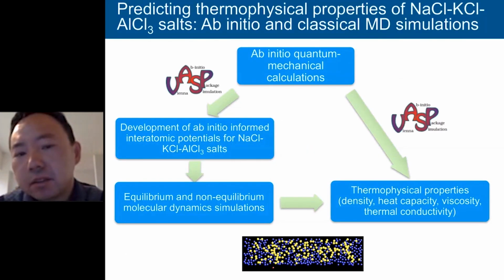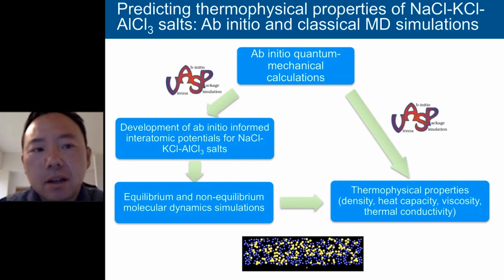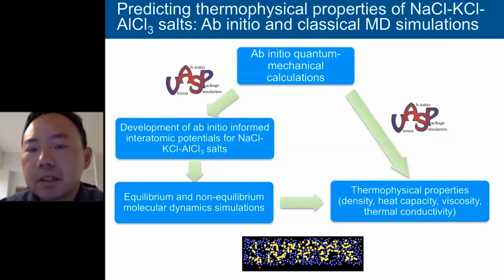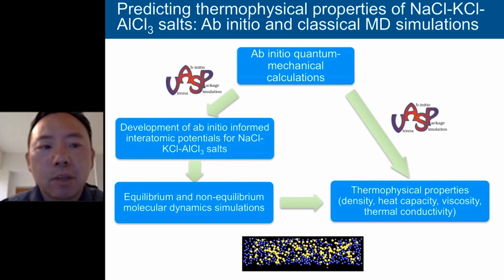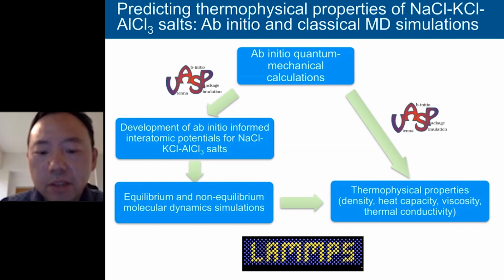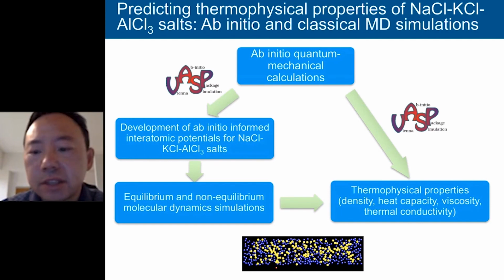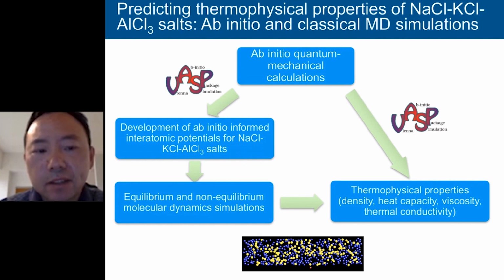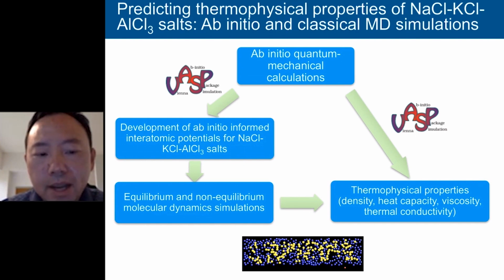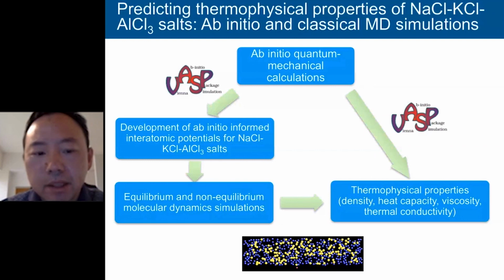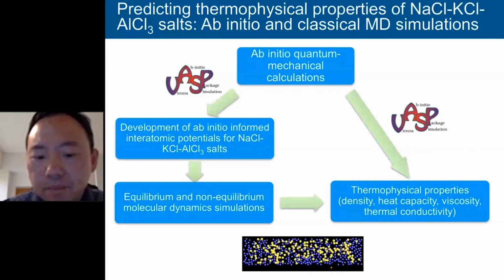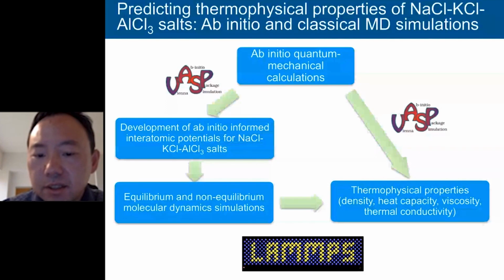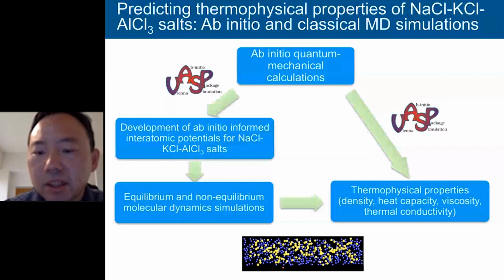So now let's switch gears to the second part of this presentation, which is my part. Here I'm using Ab-Initio and classical MD simulations to obtain the thermophysical properties of the ternary sodium chloride, potassium chloride, and aluminum chloride salts. The fundamental idea is that we use Ab-Initio calculations to do two things. First, to provide enough data to train interatomic potentials for these ternary systems. This potential will then be used in both equilibrium and non-equilibrium MD simulations with the LAMMPS code to calculate many of the thermophysical properties, such as density, heat capacity, viscosity, and thermal conductivity.